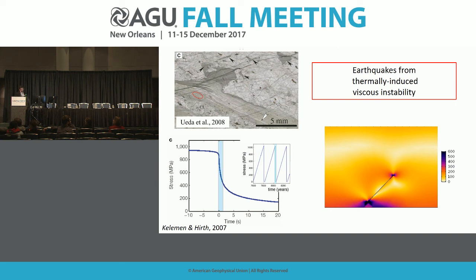So Peter Kelemen and I worked on a similar type of idea for understanding intermediate focus earthquakes. The idea there was to take those deep outer rise events and imagine that you've created a really fine-grained peridotite, and then upon subduction, when it heats up, you get a shear heating instability because that fine-grained stuff deforms much more easily than everything around it. There was a kind of magic temperature range of around 600 to 700 degrees where this would create a thermally induced viscous instability over a few seconds. You get a big stress drop.